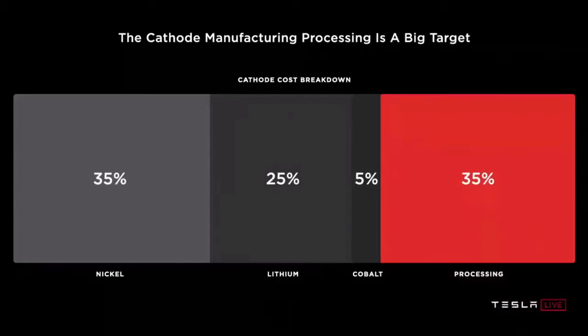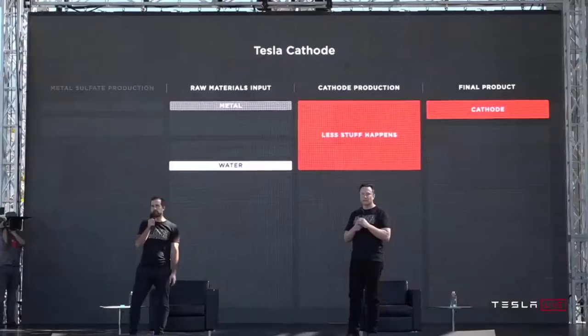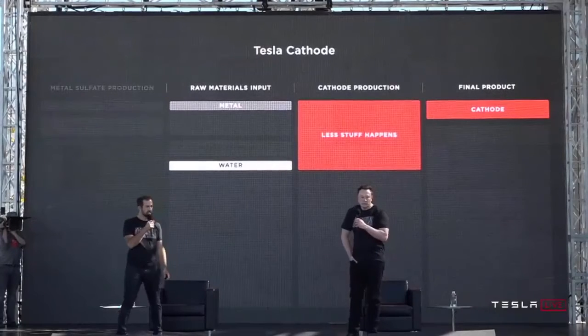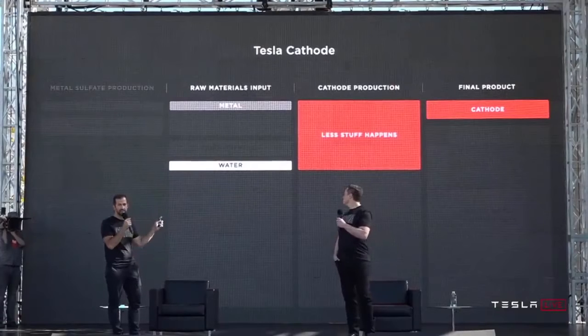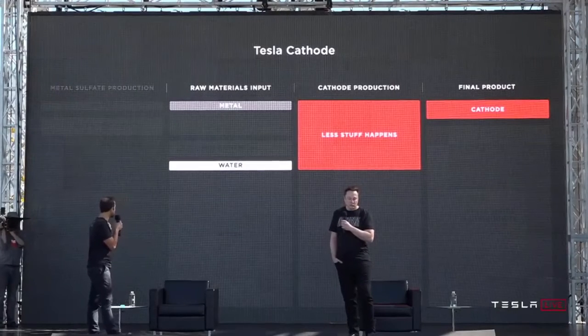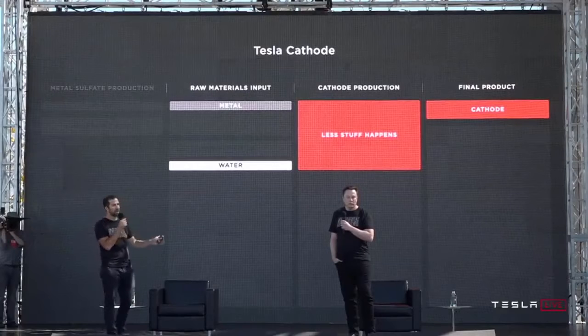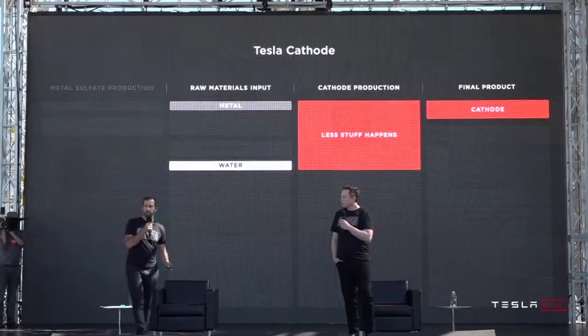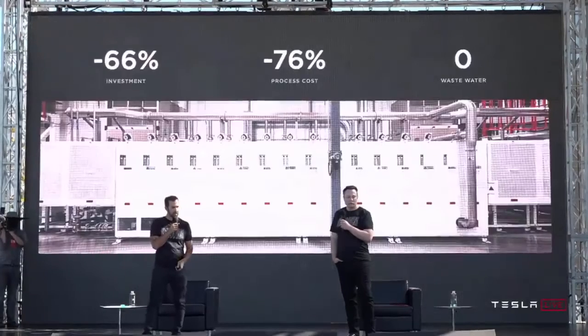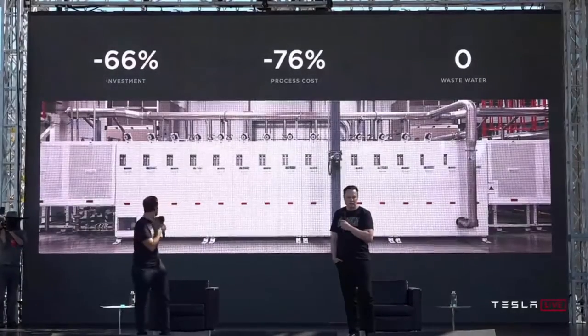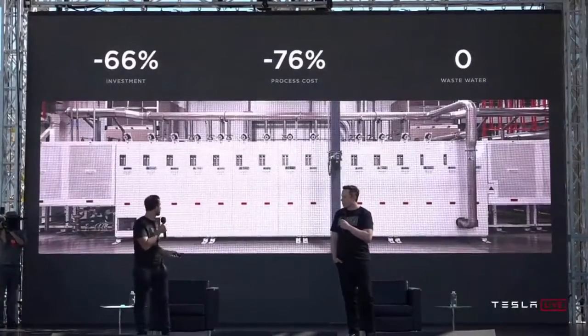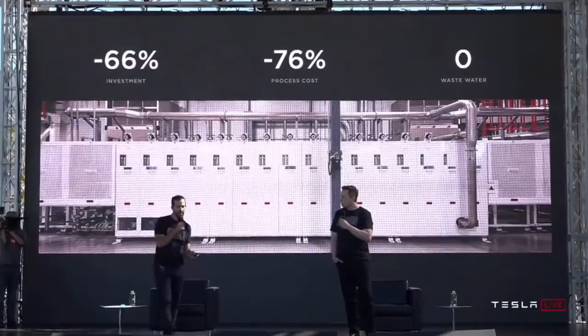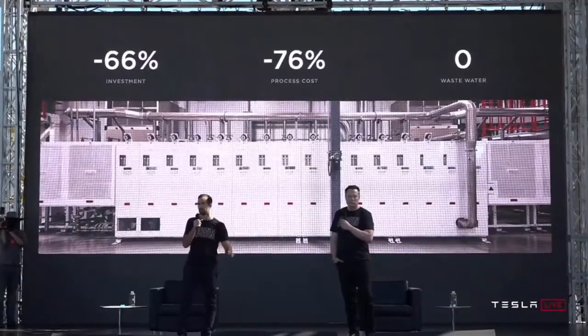35% of the cathode dollar per kilowatt hour is just in transferring it into its final form. And so we see that as a big target, and we decided to take that on. And that's what we're proposing here with our process. As you can see, a whole lot less is going on here. We get rid of the intermediate, metal, water, final product cathode, recirculate the water, no wastewater at all. And when you summarize all of that, it's a 66% reduction in CAPEX investment, a 76% reduction in process cost, and 0 wastewater. Much more scalable solution.